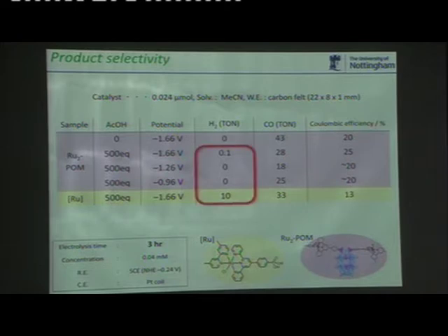When we take the polyoxometalate, the hybrid system, we can add quite a lot of acid, and actually I've got newer data that I haven't added. This even goes far beyond this, and actually we can even further improve it. Here, at different potentials applied, we see essentially the CO2 conversion being maintained, although decreased somewhat on these data, with similar efficiency, but we see essentially no hydrogen evolved. So this is really nice.